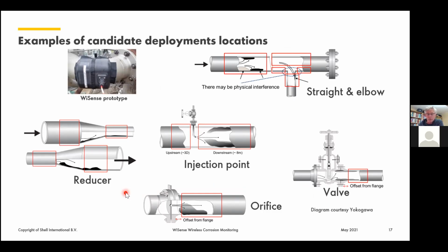It also works on top of a weld, which means that any pitting generated in the root of the weld is also measured. And that's a strong aspect of the technique, because on the inspection side, you need much more complicated NDT, non-destructive testing techniques, to measure what is going on in the root of a weld than in the parent metal next to it. So the capability to monitor over the top of a weld is a very strong one.